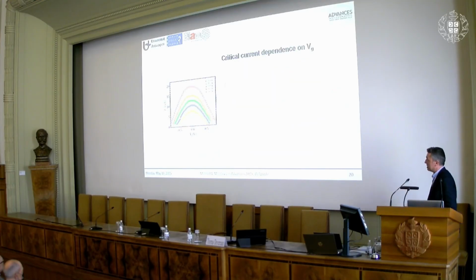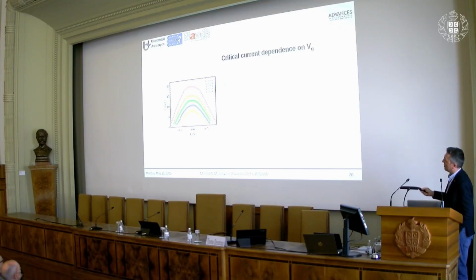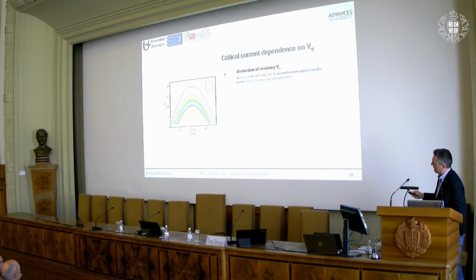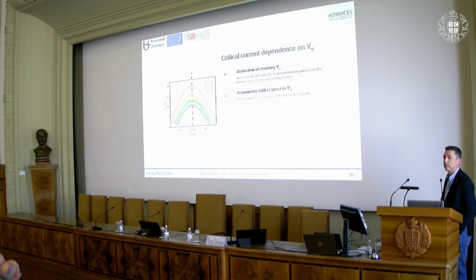So this is the result. As a function of temperature, we have a strong effect of gating on the critical current, and the operating gate voltage is reduced to below a volt. It used to be tens of volts. Then we have asymmetry. It's no longer symmetric, it's asymmetric. I don't know if it's very clear, but it's not bipolar.